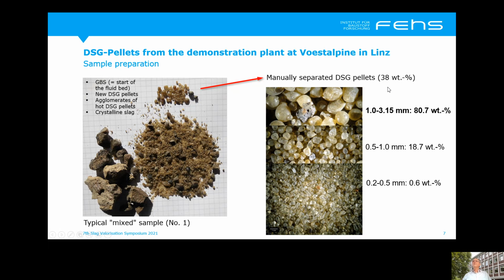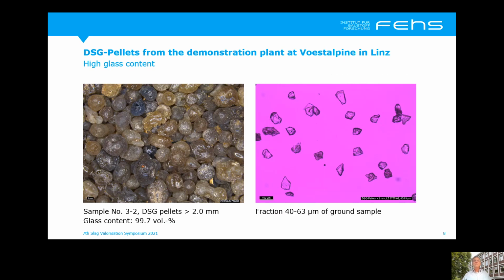The DSG pellets account for about a third, in that case 38%, of the whole sample, and the main part of the DSG pellets was between 1 and 3 millimeters. The glass contents were always very high, about 100 volume%.